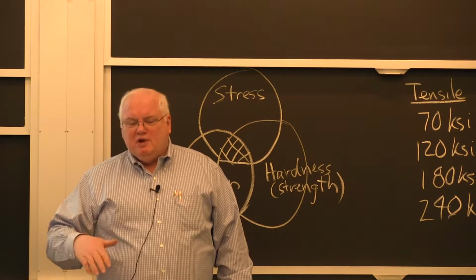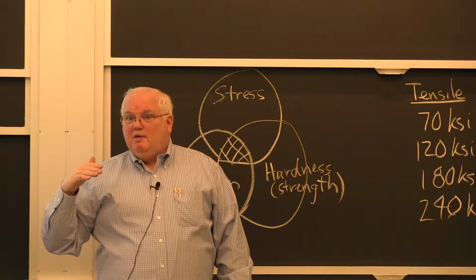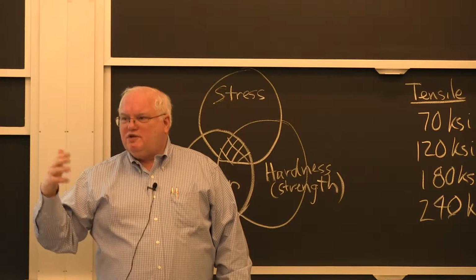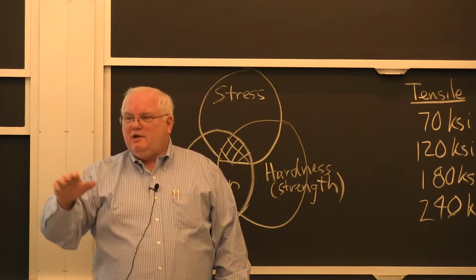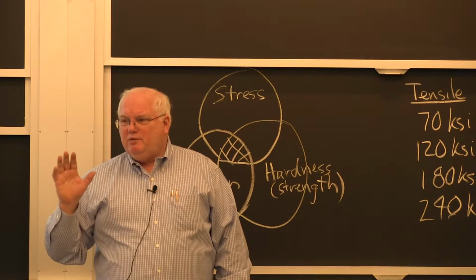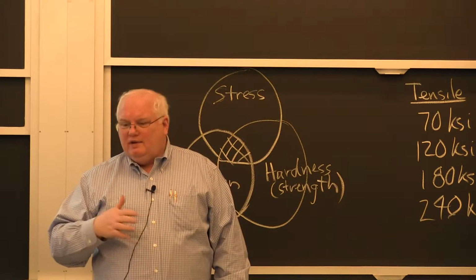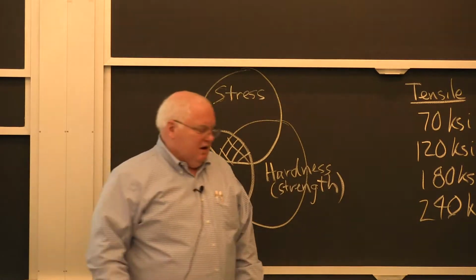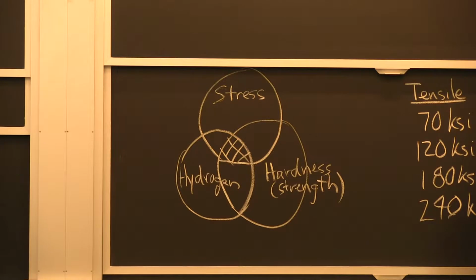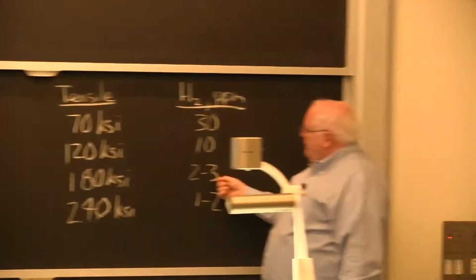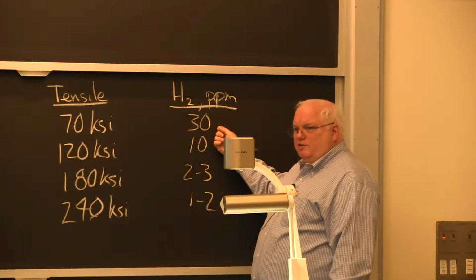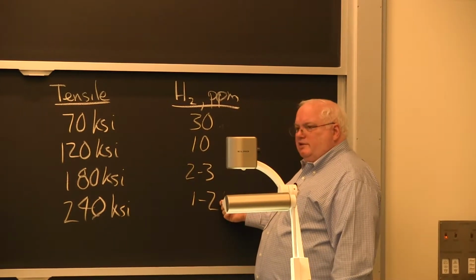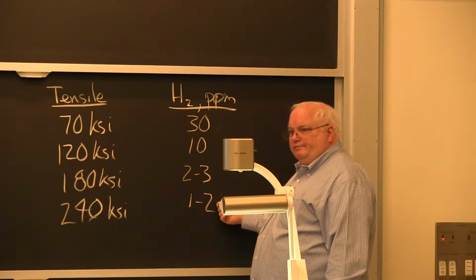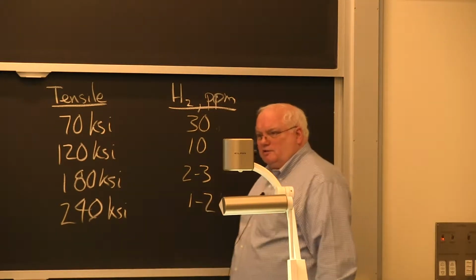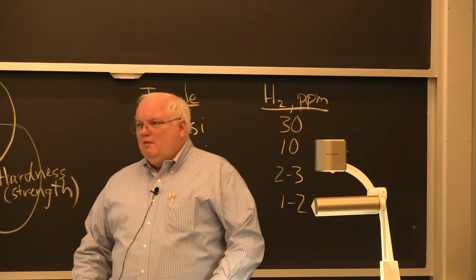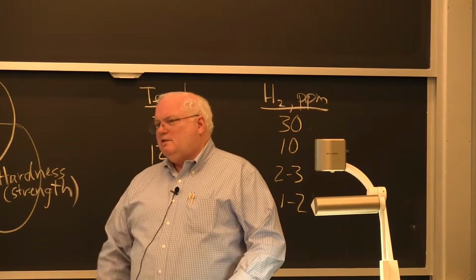You have hydrogen traps. And people have studied what temperature the hydrogen is released from the traps. And so typically 375 Fahrenheit is the number that people use. There's still hydrogen comes out above that. But in general, it's a time temperature diffusion thing. What's the concentration? Up here in these types of steels, 1 hour at 375 is plenty. In these steels, you might need a day at 375 to get to these levels, at the higher strength levels. There's not a fixed number. But I'm going to show you something that allows you to calculate all this.